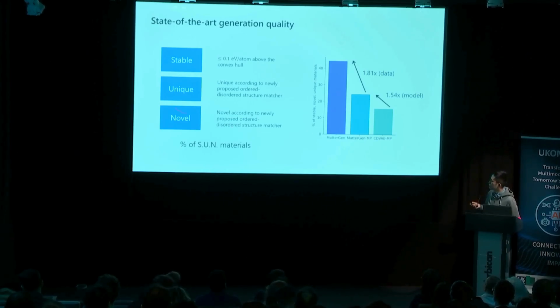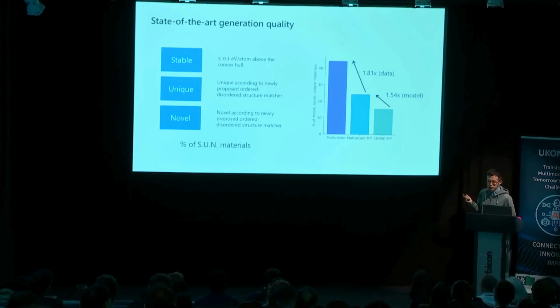We evaluate all the models that were available back then in the public, and we show that MatterGen, by doing this architecture innovation, has a 1.5 times improvement compared with the state of the art back then, called CDVAE. And because of this additional data accumulation, this gives us another 1.8 times performance, as you can see. So the improvement in the model comes from both the model architecture improvement as well as the data.